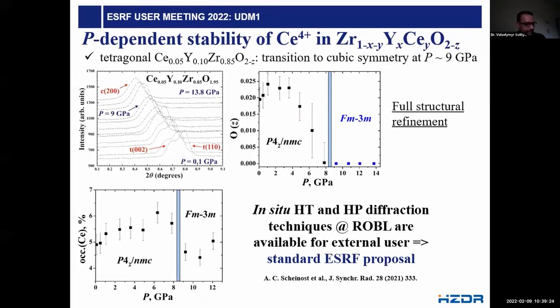It's quite nice, but most important is what happens with these incorporated cerium atoms, which are surrogate ions for tetravalent actinides. We were able to refine their occupancies throughout the studied pressure range, and what we found is that within the error range, the occupancy of these guest cerium ions remains stable. I would also like to say that these in situ high temperature, high pressure diffraction techniques are available for external users through the standard ESRF proposal system. And if you have some ideas, you're welcome to contact us to discuss.